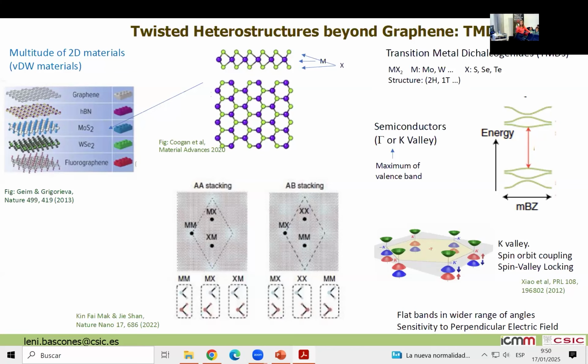Well, so what has been observed for the dichalcogenide in bulk can be quite different. Already even the dichalcogenide from the bulk to the monolayer. But here you change all the band structure. You really create flat bands which are associated to how the two layers see each other. So in the dichalcogenides, people are observing a completely new world, as impressive as the one of graphene or even more. I have mentioned a couple of cases, but the field is really exploding. But I think it's intrinsic, associated to these flat bands.